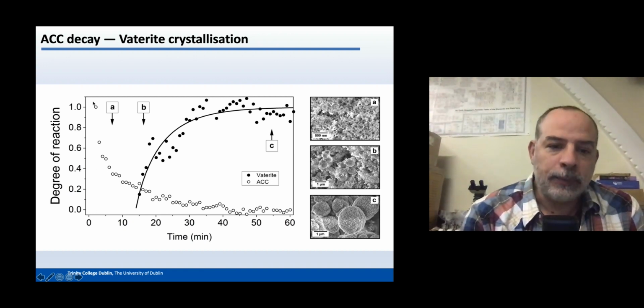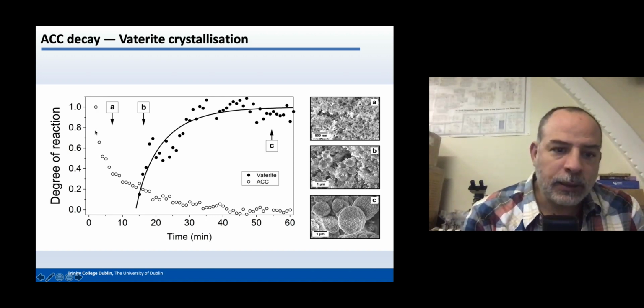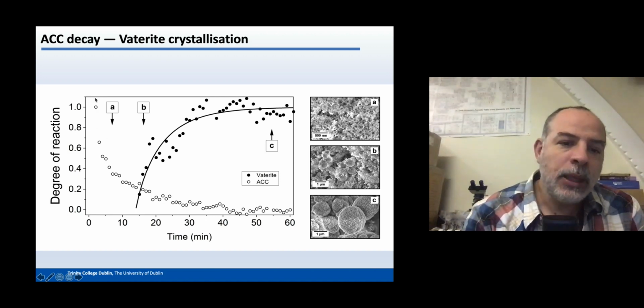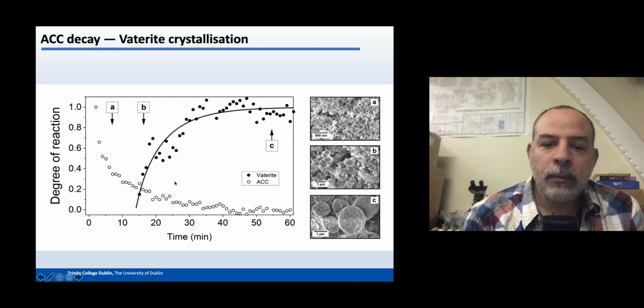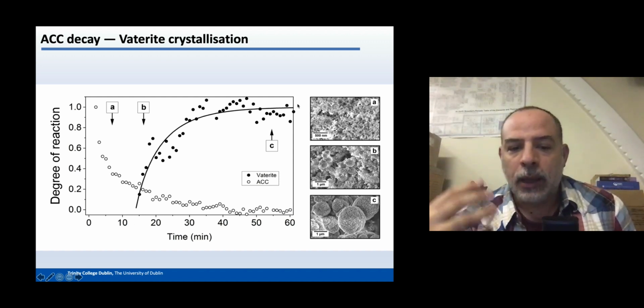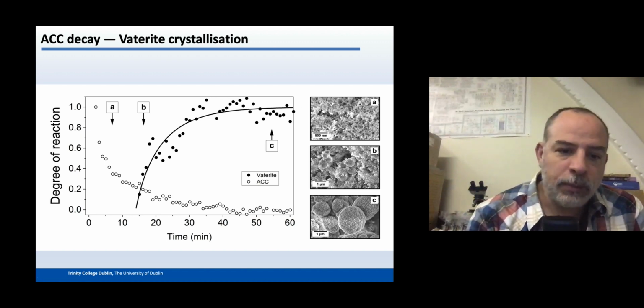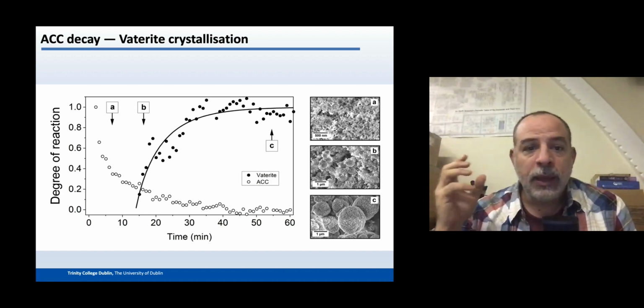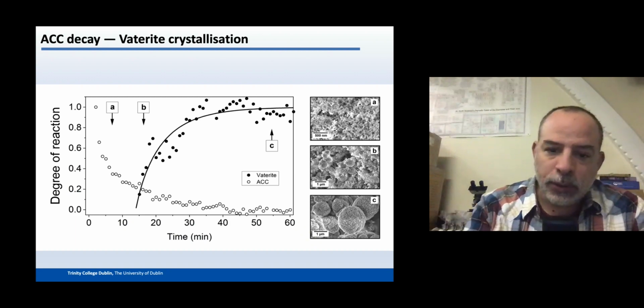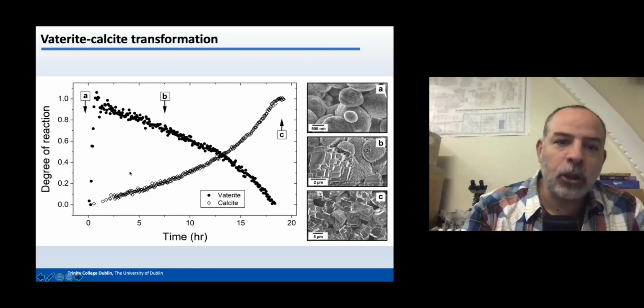So what do we have here? We have amorphous calcium carbonate. These are these white dots, which are breaking down, and quickly vaterite is forming. This happened at low temperatures, about 7.5 degrees C, and then after this process what we see is that calcite was growing from vaterite.